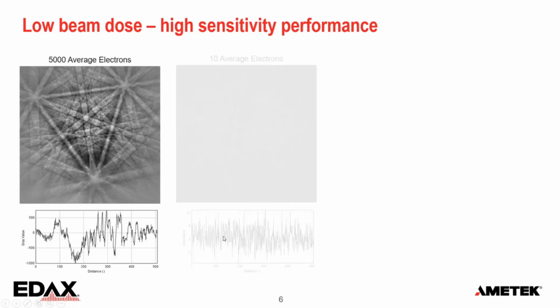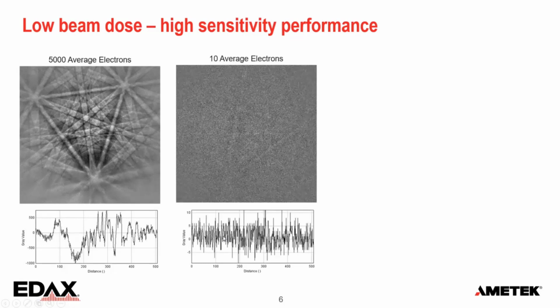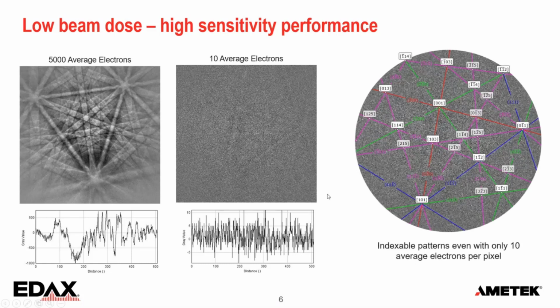If we don't want to wait that long, we can collect a pattern with 10 electrons on average per pixel. And when you then look at the chart at the bottom, it's very noisy. And this is just a few electrons in general coming in, but the bands are still recognizable. And that is actually enough to index the patterns and get good orientation determinations.